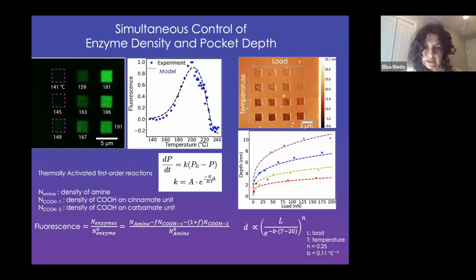Okay, this slide shows instead how we can control the enzyme density with the temperature, so the percentage of amine groups, and the pocket depth, meaning the 3D aspect, right? How deep is the indent that we are making. So we can calibrate, so we can change temperature and load. This is showing the density of the amine groups. This is the fluorescence showing how it changed with the temperature. This is instead a calibration where we change temperature and load at the same time. So you have the different curves here of indentation versus load for different temperatures.